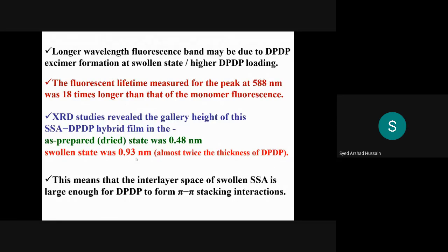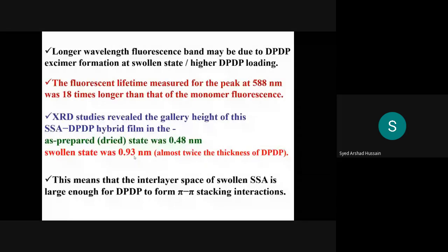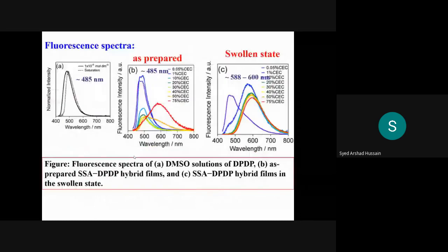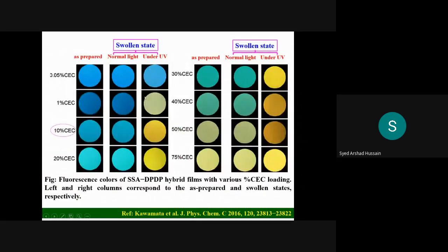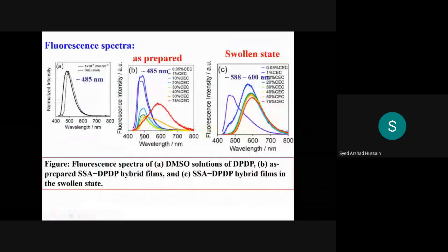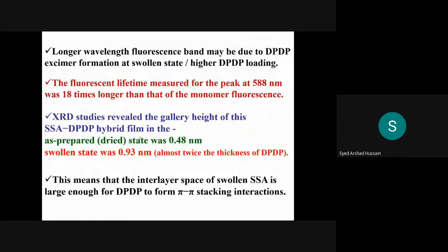So this confirms that in dry conditions... I'm sorry, I forgot to tell one thing. Here, this is UV, and in this normal experiment we put some solvent on the as-prepared film, then we did this experiment. This is after normal light, then UV light. So when we put some solvent, swelling occurs. Due to swelling, the gap between the clay layers increases, and two molecules come in between the layers, form a pi-pi stack, and form an excimer.